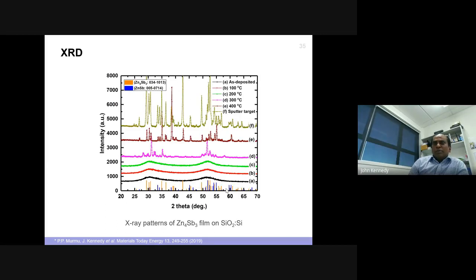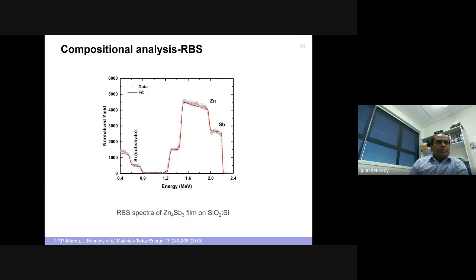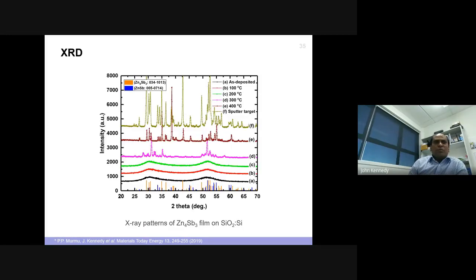Then we looked at the structural analysis again. We see a mixed phase of zinc 4 antimony 3 and zinc antimony. So they are both observed commonly. This is interesting, because some techniques can only do a single phase, and by tuning some of our parameters, we can have a mixed phase. Then you can actually take one phase and reduce the other phase by annealing it.